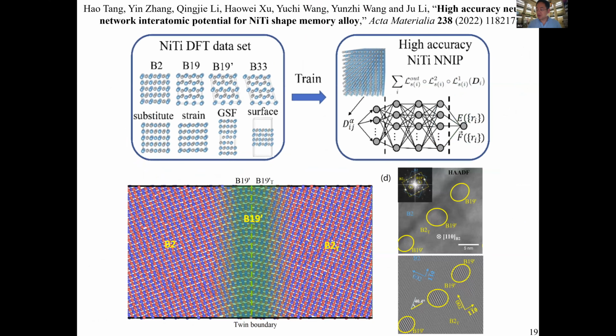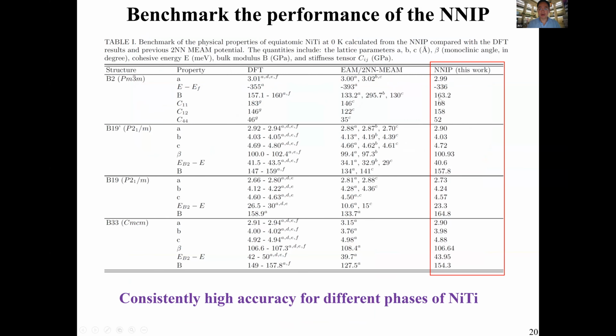So switching gears a little bit to metallic systems. We have also used neural network potentials to fit a well-known tough case, which is the nickel titanium shape memory alloy. The reason it's a tough case is because at 0 temperature, these three phases, B2, B19 prime, and B33, are very close in energy. In fact, the room temperature stable phase is phonon unstable at 0 temperature, so it's really stabilized by the vibrational entropy effect. By doing neural network fitting, we're able to pretty much reproduce the basic properties of these competing phases.